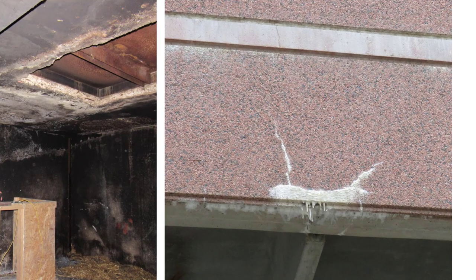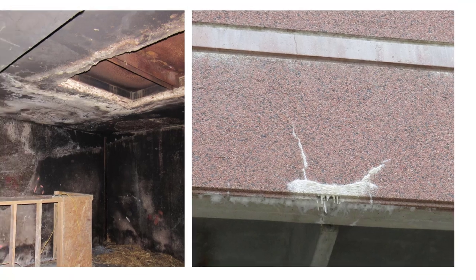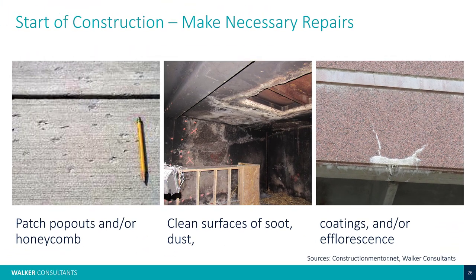Now, again, we talked about coatings previously. If you do bond testing with coatings, you might be able to prove that a certain coating has the competency to go right over the top of it. Or you might find that you have to remove that coating in order to install the carbon fiber. And then certainly efflorescence, an obvious indicator of leaking. You want to get that all cleaned up. You want to take care of the cracks, that type of thing.